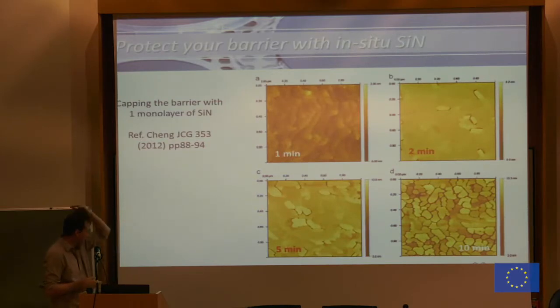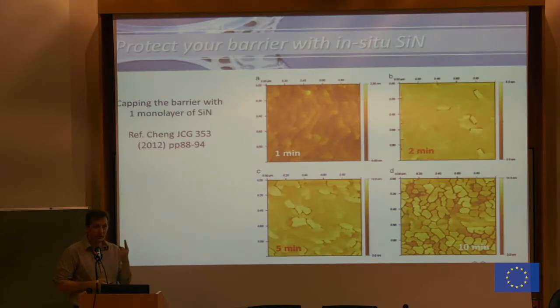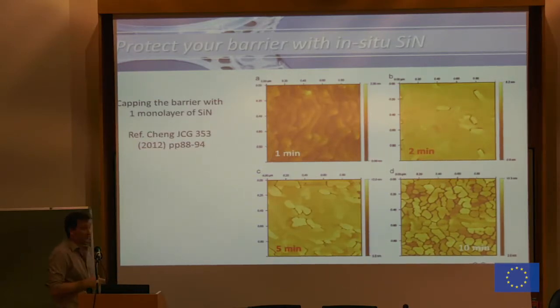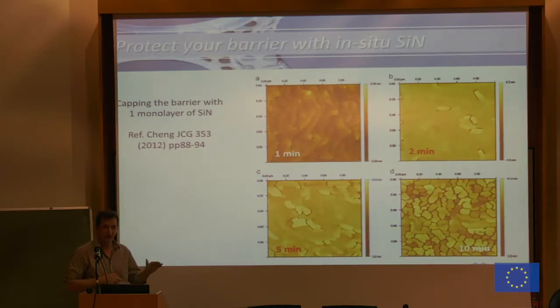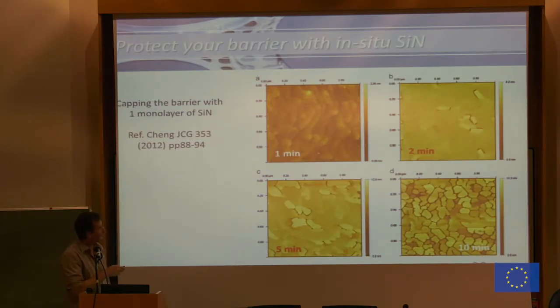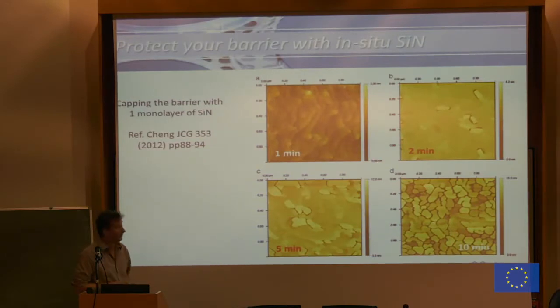And in fact, this is an illustration of that point. It is a very nice experiment where we have grown gallium nitride, aluminum gallium nitride layer stacks, and we have capped them with one monolayer of silicon nitride, one monolayer only. So that is half a nanometer. It is not a lot of material. What we did in the experiment was vary the time between the end of the growth of the barrier and the beginning of the growth of the in situ silicon nitride layer. And it is very clearly shown here that up to 1 minute at high temperature, your surface is stable, so you only see the atomic steps that you have before. But the longer you wait to cap your material, the more of these grooves form and the relaxation of your barrier occurs.